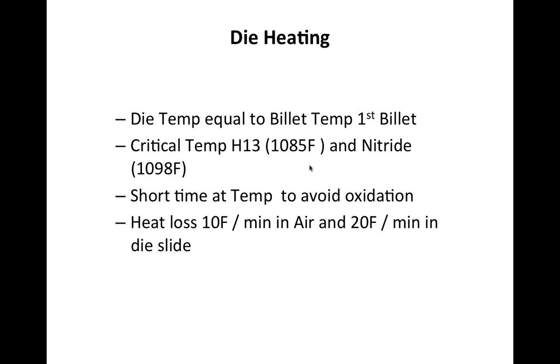We know that H13, or 2344, anneals at about 1,085 degrees Fahrenheit, and we know that the nitride layer on the die bearing starts to degrade at about 1,098 degrees. So when we're heating the die, we want to make sure that we never go above these temperatures.